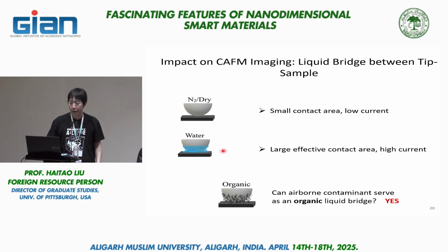And within the conductive AFM community, people know this water meniscus model. If you have an AFM tip, so this hemisphere is the tip of the AFM probe, it comes down to the surface, and then that contact would create a capillary condensation effect to accumulate water. And that water would change the local conductivity behavior, and that could increase the current measured in a CAFM experiment. And what we showed recently was that this layer of organic contamination actually produces the same kind of effect. So you would see this modulation of electrical current in the presence of hydrocarbon contamination, even if you are working in a dry environment.